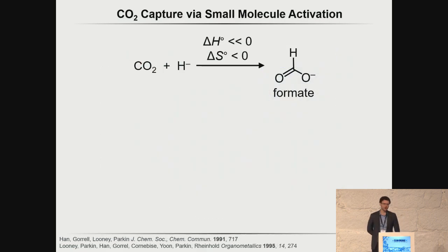So we thought about this process from a simple energy perspective. If our Gibbs free energy is penalized by our entropy of adsorption, we need to offset it with high enthalpy of adsorption. And in our interpretation, we thought about that as CO2 functionalization can provide sufficient enthalpy of bond formation to overcome this entropic penalty.